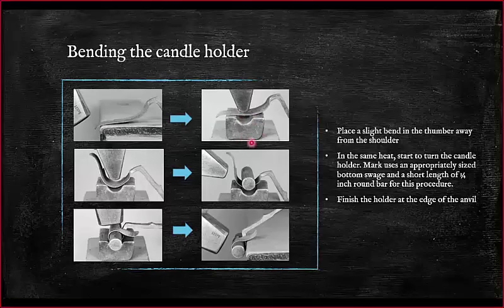The first top left slide is showing first you go back to the top of your anvil and bend the thumb out of the way, just a nice little sweet spot. We're bending away from that shoulder. Then you come over and you're using another swage. And I'm using a 7/8 bottom swage because I've got a 3/4 candle. I've got 1/16th thick material. So by the time I wrap everything, it should be 7/8 diameter. And hopefully I've relieved the corners a lot.